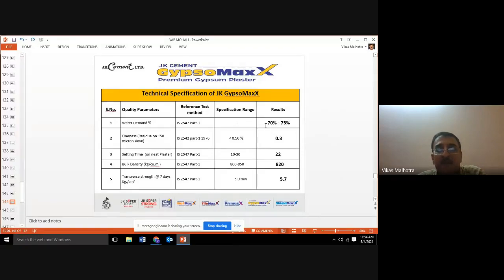Specifications: water demand is 70 to 75%. Fineness is 0.3. Setting time is around 22 minutes. The higher the setting time of this product, the better it is. The reason is that the applicator wants some time to apply this product. This gets set very, very fast, so they need some extra time in which it should remain in plastic stage. So we have tried to give that.